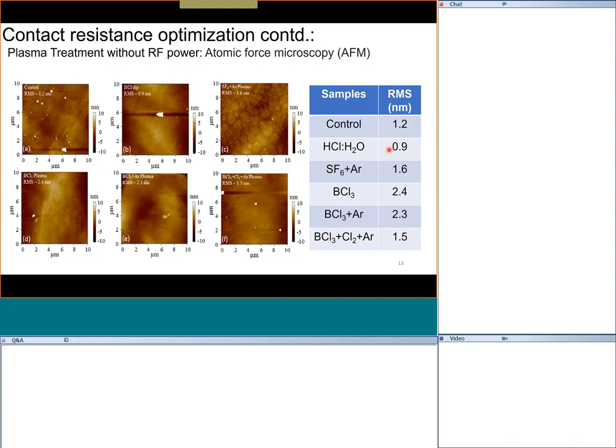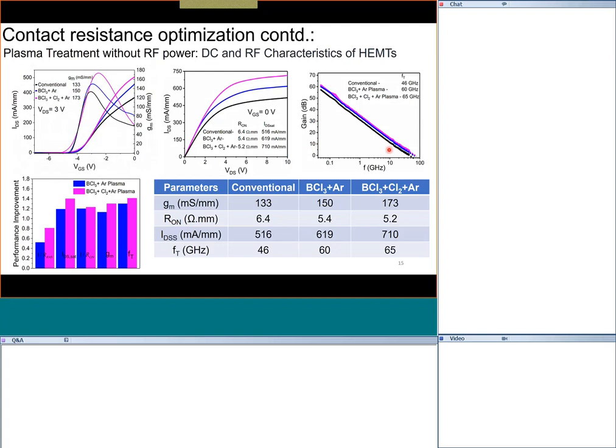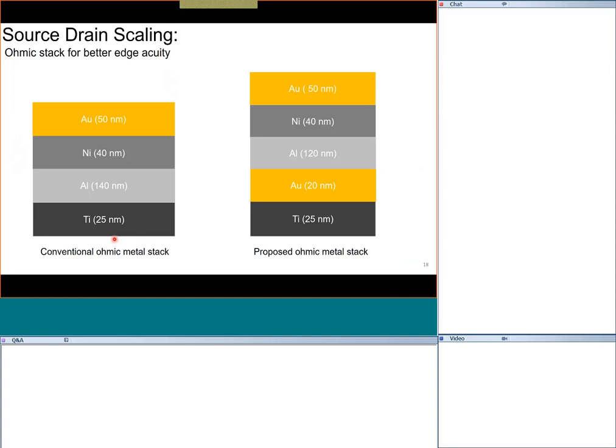If you really want very low surface RMS roughness, you use another recipe; if you want both low contact resistance and low surface roughness, you need yet another approach. After applying the plasma treatment and making the transistor, we see significant performance improvement. For a transistor with approximately 250 to 300 nm channel length, the unity current gain frequency improved to about 65 GHz after this improvement — improvement across all metrics.